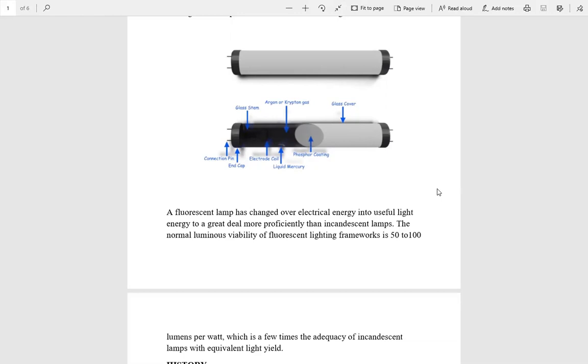Generally, small plates are attached to the filament to protect it from electron bombardment and to reduce the wattage loss at both ends. The electrode is similar to the incandescent lamp filament, but an exemption is that this filament is dipped in a mixture of barium, strontium, and calcium carbonate. It is baked during manufacturing to become oxides, and thus it becomes capable of providing the abundance of free electrons easily.